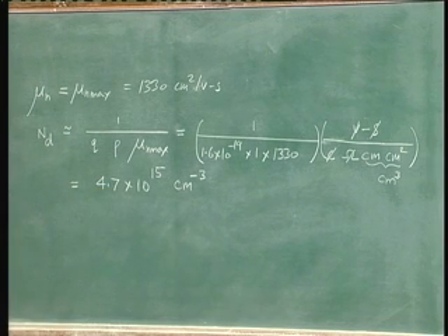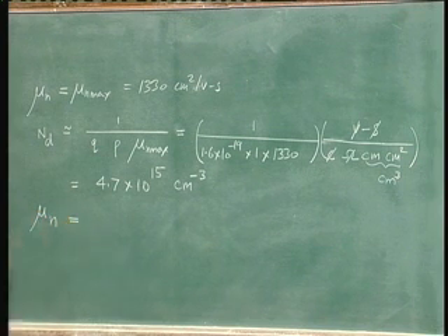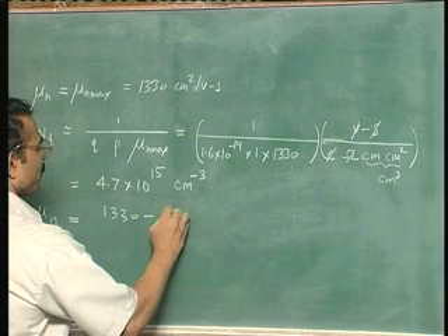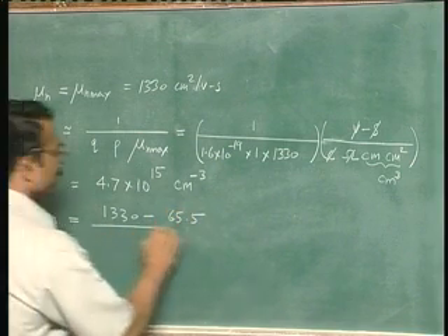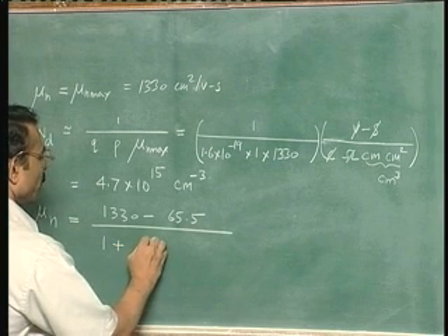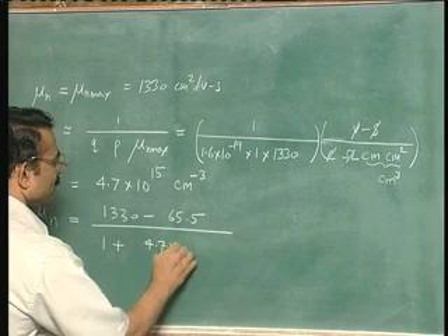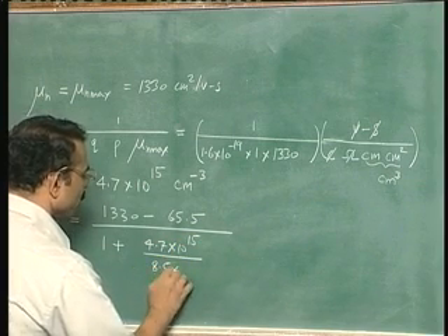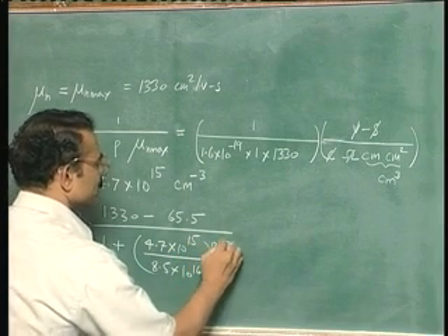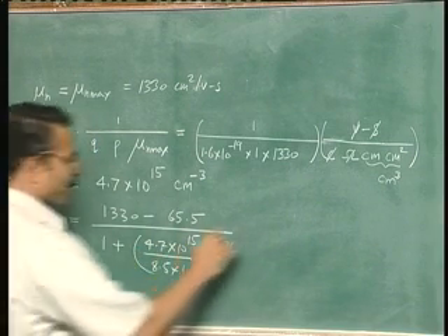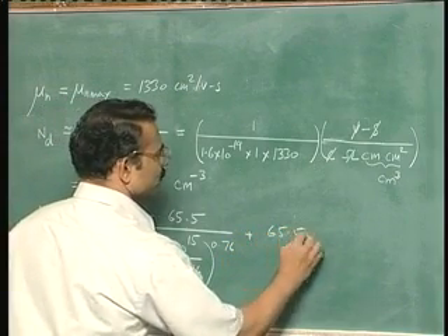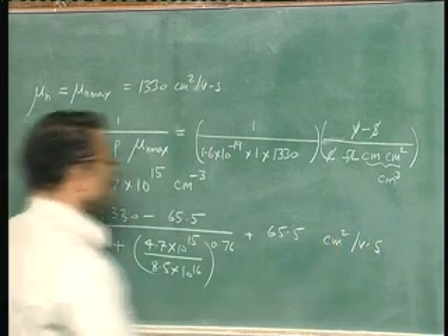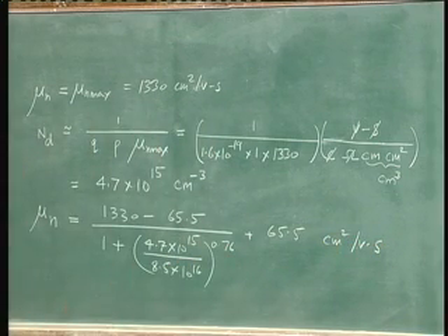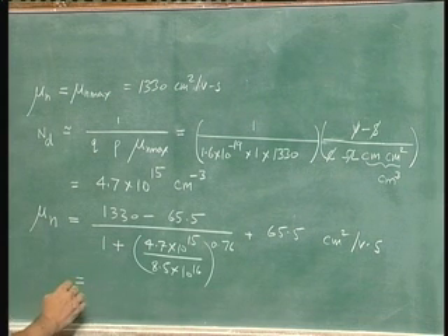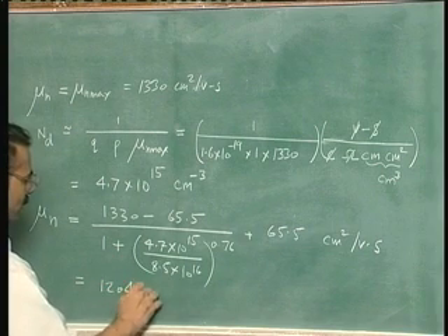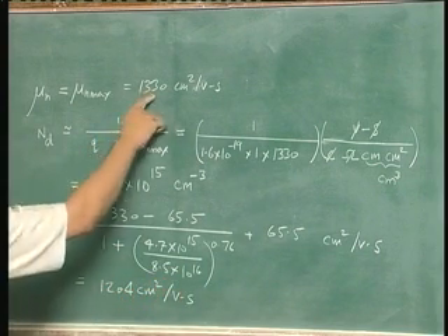Now you use this value of doping and find out the mobility. Now your mobility you can write using this formula, 1330 minus 65.5 divided by 1 plus the doping, that is 4.7 into 10 power 15 upon 8.5 into 10 power 16 whole power 0.76. This formula we had shown on the slide earlier, plus 65.5 centimeter per volt second. So you use this formula for mobility as a function of doping at 300 K, and then the result will be a mobility of 1204 centimeter square per volt second instead of 1330 that we assumed earlier.